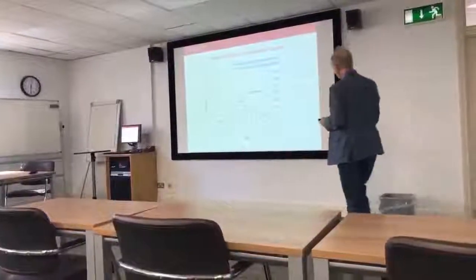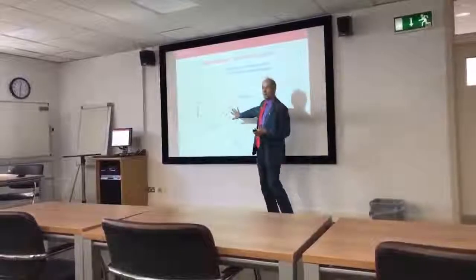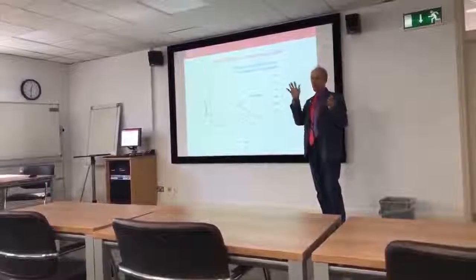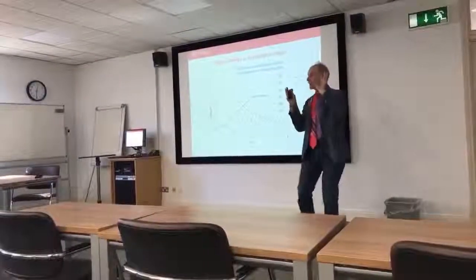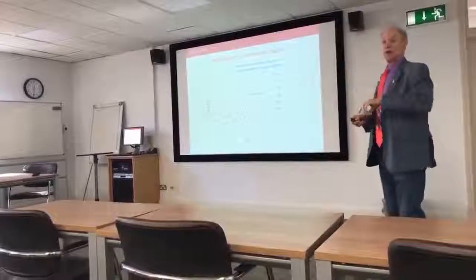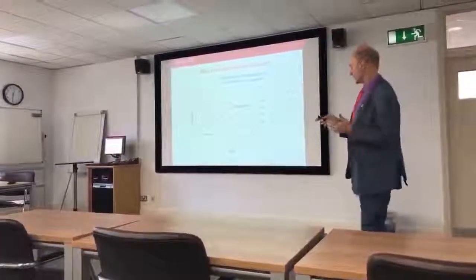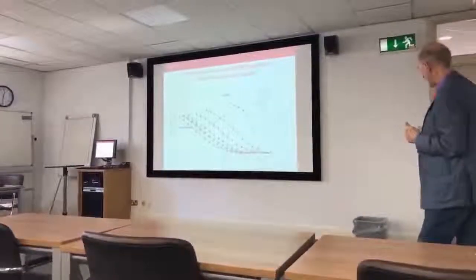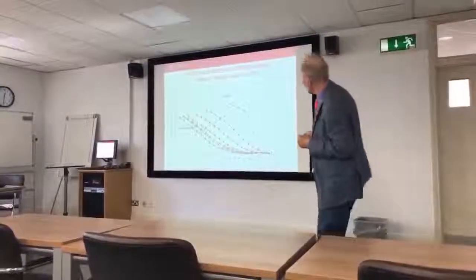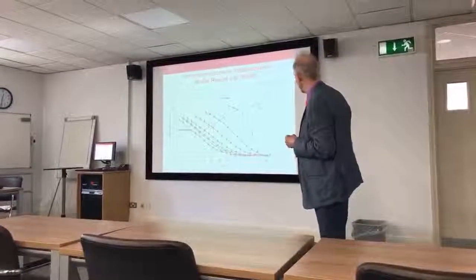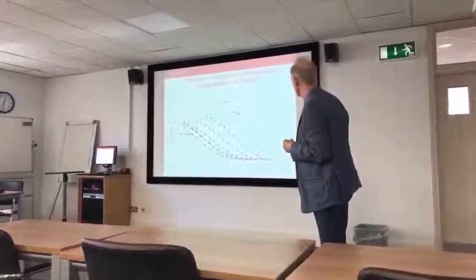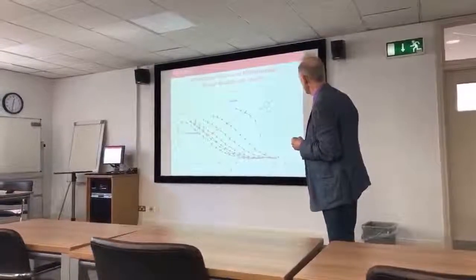Well, the key thing about this kind of probe is, are we really monitoring what's happening in the matrix? Or are we just monitoring what's happening in the probe? Is this probe just responding in some funny way to the matrix, or is it really accurately reflecting what's happening in the matrix? And one of the best ways to get at that question is to use a different kind of molecule with a different structure that will interact in a different way with the environment. So let's look at another molecule. Look at vanillin. Vanillin has a lifetime of a couple of 100 milliseconds in a nice rigid matrix. And if you put it in similar sorts of environments, I would say starting with glucose to maltoheptaose.